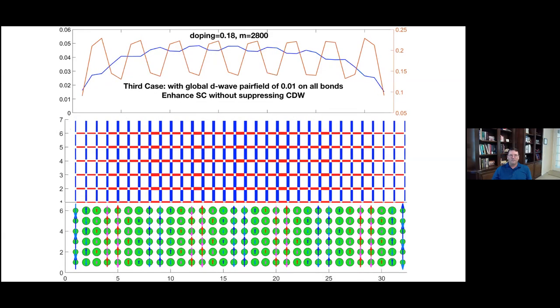And then here's a third case. Again, just slightly different doping, slightly different initial conditions. But the main thing that's different here is that we do a different type of experiment where we put a pair field, which is pretty weak, 0.01, across all the bonds. So we're really trying to force this stronger pairing state. And we get a very strong pairing response. It hasn't killed off the stripes. We still see stripes. Their amplitude in the density is not too large, but you still see this spin pattern.